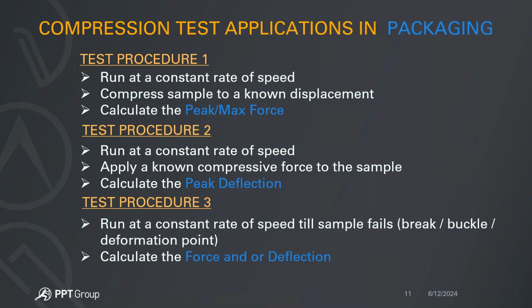In that first scenario, in test procedure 1, the test is run at a constant rate of speed. The sample is compressed to a known displacement, and then the calculation yields a peak force or a maximum force at that displacement, the target displacement. Test procedure number 2 involves running again at a constant rate of speed and applying a known compressive force to the sample, and then calculating exactly how much the sample deflected.